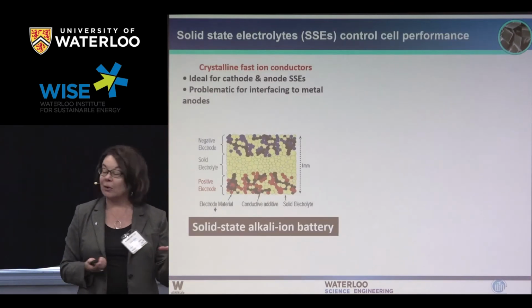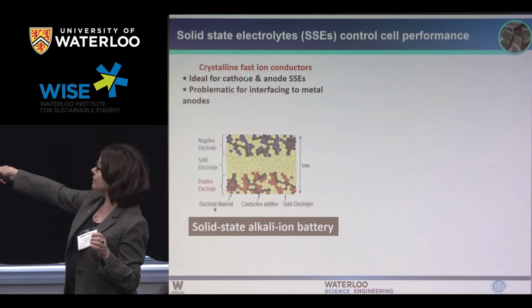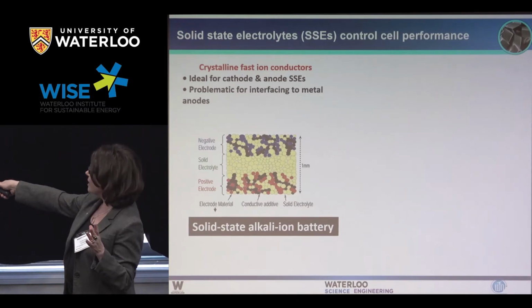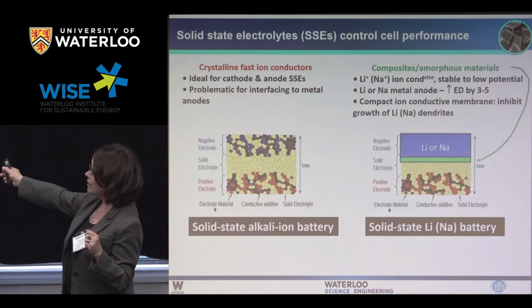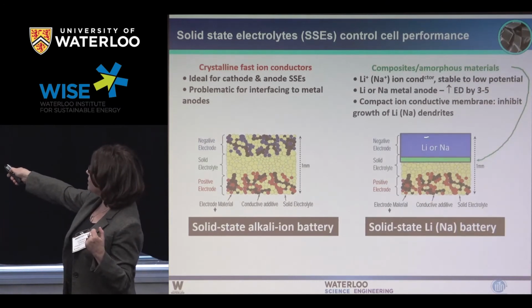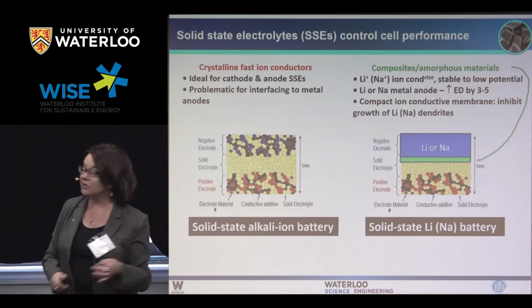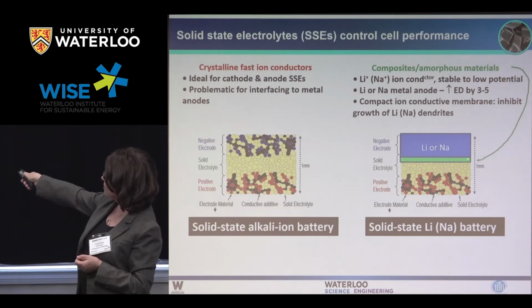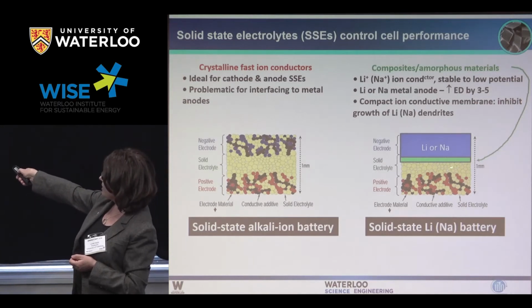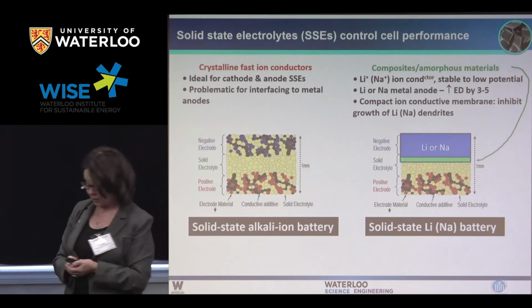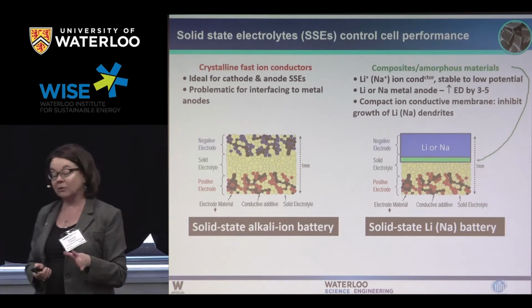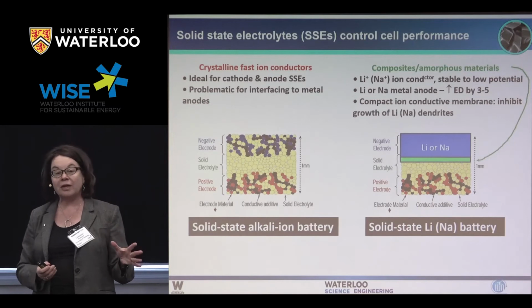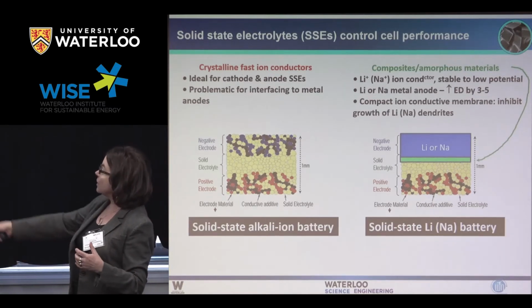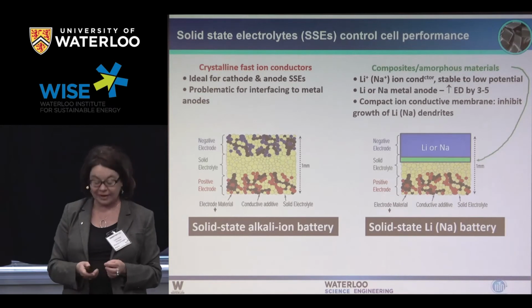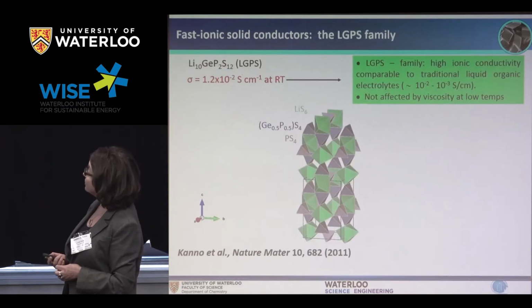So there's two ways of approaching it. One is to make new solid-state electrolytes and try to interface them in cells like this, and we call that a solid-state alkali-ion battery, and it can be sodium or lithium. And the other is that we use a metal anode, which really improves the energy density, and then we usually have to put some sort of interfacing ion conductive membrane in place, because usually this electrolyte reacts with lithium or sodium metal. So these are sort of two approaches, and this is what is, I would say, consuming most of our community at the moment, trying to make these work, and that's sort of where things are going in the next 10 years.